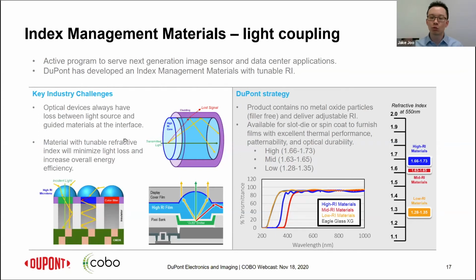Whenever we want to assemble the material into co-packaged optics, of course there's a fiber, and there is either a polymer waveguide or something that needs to be fixed or coupled to each other. To be able to couple that, you need some type of material, unless you just want an air gap to guide the light, or even assemble those fibers with adhesive that has the right refractive index, because if it's not, you can leak out the light or trap the light.